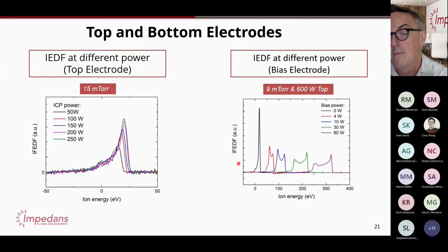Yeah, I think I've answered it. I think this graph actually answered that. But how much it does, there's a kind of rule of thumb actually. The DC bias is typically about half of the peak-to-peak voltage applied. So if you apply 2 kilovolt peak to peak, your ion energies are probably going to be around 500 eV on average. So that's kind of the rule of thumb.